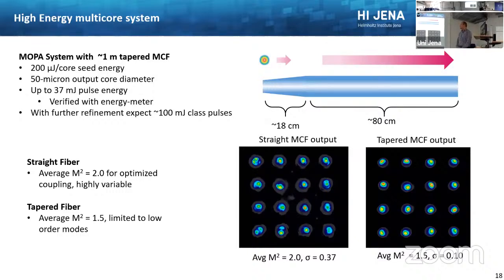Now, on this last slide, we have also been working on not going to higher average power, but actually, at a certain point, we also want to increase the pulse energy quite a lot. And we used one of those fibers which have larger core diameters. These are not single mode. They cannot really be used for femtosecond amplification and coherent combination, but you can test energy extraction with this. And we achieved here up to, let's say, close to 40 millijoule of total pulse energy, which I think has so far not been demonstrated from any fiber, at least not from a single fiber. And we think we can even go higher. And what we also tried at this point is using so-called tapers of this fiber.